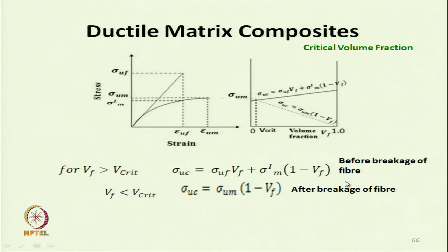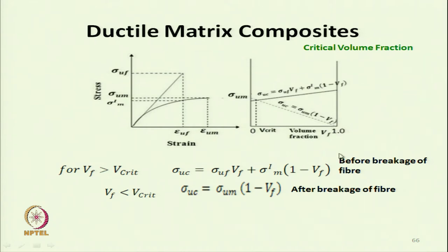Both fibre and matrix carry the load before fibres are broken. After breakage of fibre, all fibres are broken and the load is shared by only the matrix. Then the ultimate stress of composite equals the ultimate stress of matrix multiplied by the volume fraction of matrix.